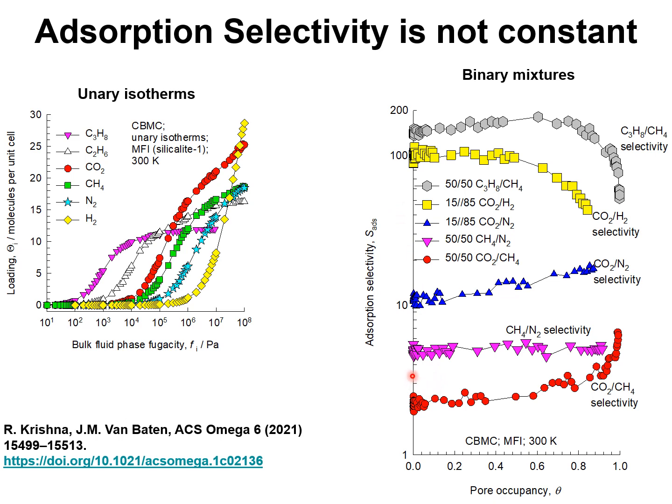So whether the adsorption selectivity remains constant, increases or decreases depends on the differences in the saturation capacities, and at increasing pore occupancies, the component that is more favored is the component with a higher saturation capacity because the vacant spaces are more easily filled up.